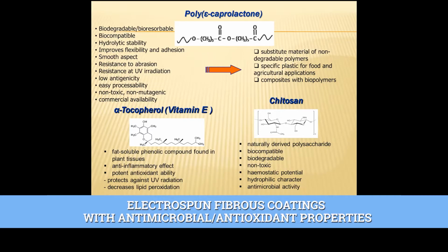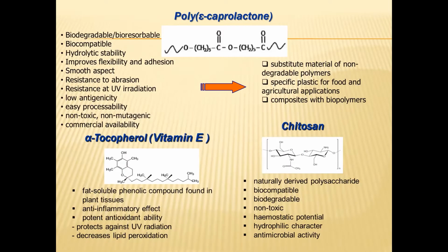Therefore, solutions prepared based on polyepsilon caprolactone and alpha-tocopherol on one side and polyepsilon caprolactone with chitosan on the other side were tested for electrospinning. By tuning the deposition parameters like applied voltage, flow rate, distance between collector and needle, combined with the solution properties like concentration, conductivity, viscosity, it's possible to obtain either continuous fibers by electrospinning or small droplets or microparticles by electrospraying